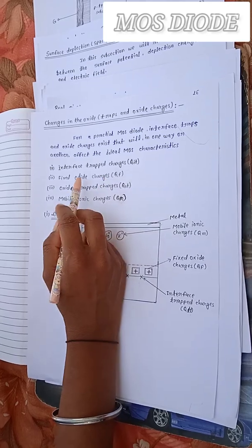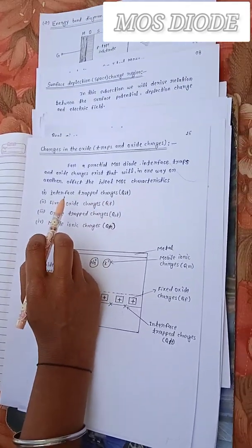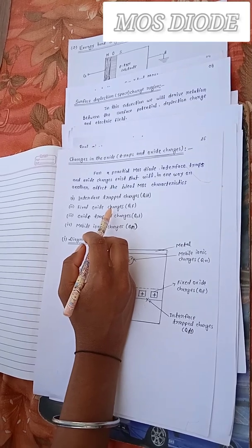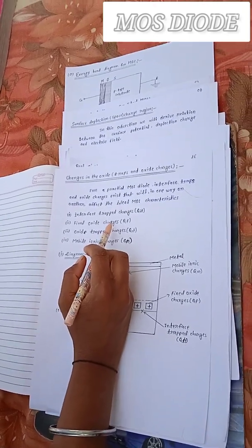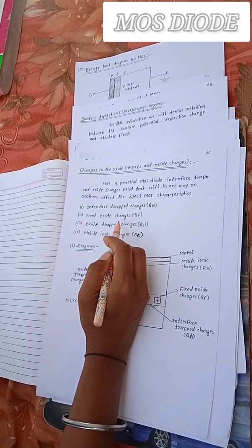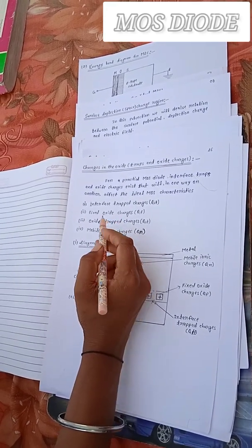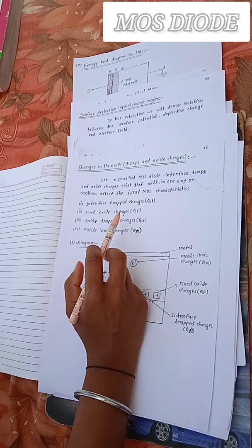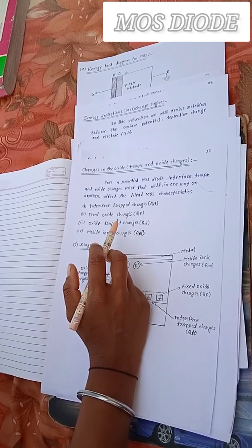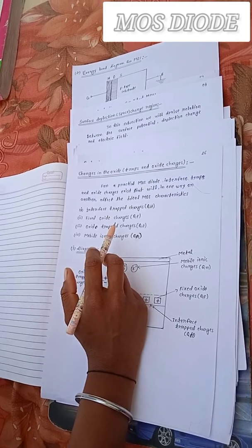Qit can possibly be produced by structural defects, oxidation induced defects, metal impurities, or oxidation caused bond breaking by hot electrons. At present, most of the Qit charges can be neutralized by low temperature, around 450 degree Celsius, hydrogen annealing.